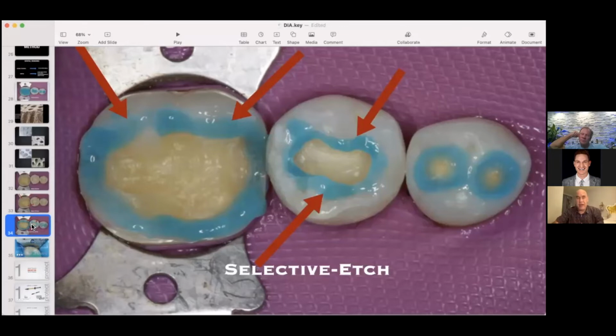Theracal, what is the bond strength? Very, very low. It's not intended to bond. It's intended to react. Okay? That's why I always tell people, put it in the deepest area. Now, what is the bond strength of your adhesive to Theracal? Super good. Why? Because it has resin. And because it has resin, your bond strength is in the 30s. So it's fine. The problem is your bond strength of Theracal to the dentin, but it's not intended to have any bond strength.